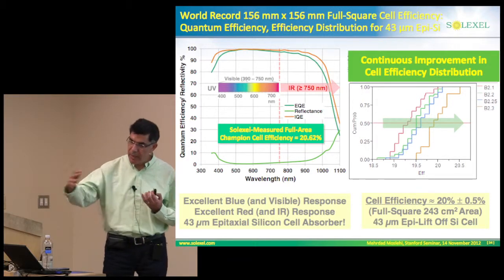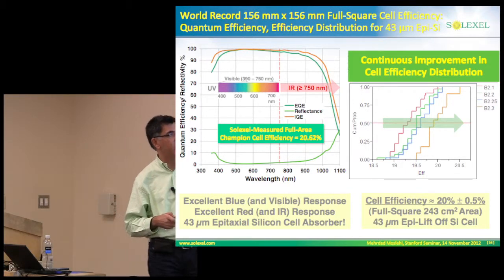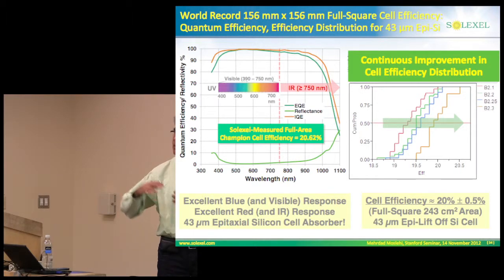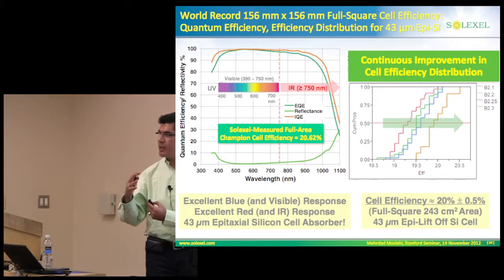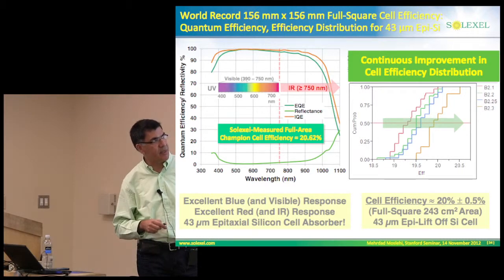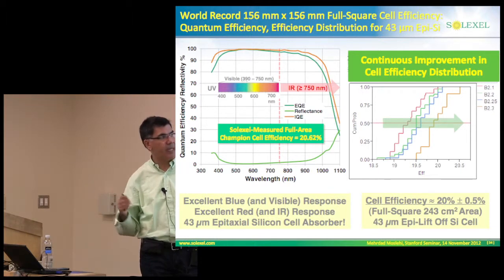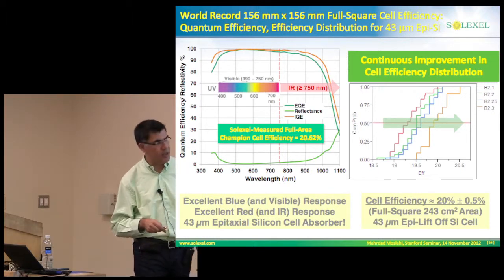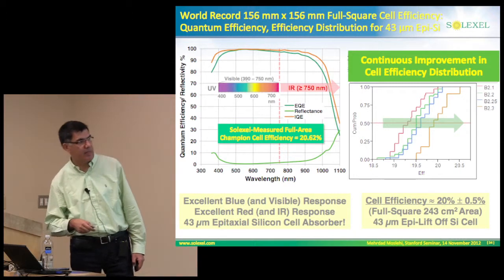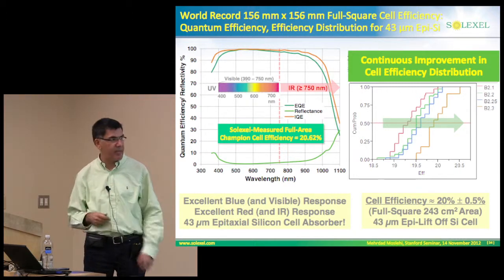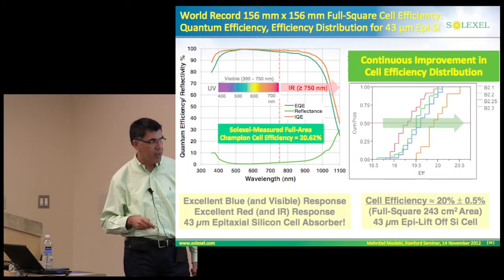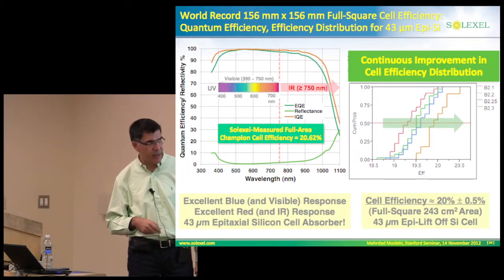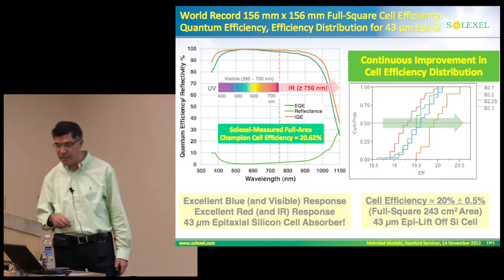We have also been climbing the efficiency ladder with time, and this has been very nice momentum, also tightening our distribution in our line. This represents our current baseline flow with a mean efficiency around 20%, and the latest distribution is around plus minus 0.4%. This is range, max mean range. So this is all for full area cells with 43 micron absorber thickness.